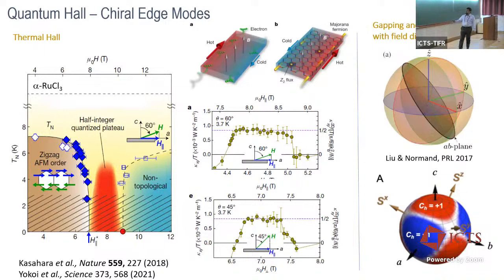And eventual results by Yukitoshi Motome and another group basically confirmed what was proposed by Liu and Normand in their PRL paper, which shows in which direction you should get a gapped and in which direction you would get a gapless phase. So the directions in which you expect to not have a gap, which is field along the b direction and these white regimes, they showed that you don't get a thermal Hall plateau, but in the other directions you do. So that was nice to see.